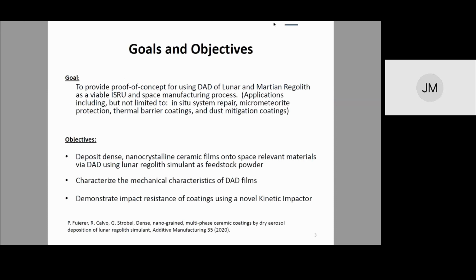The objectives were to deposit dense nanocrystalline ceramic films onto space-relevant materials using DAD with lunar regolith simulant as our feedstock powder. I also set out to characterize the mechanical characteristics of these films using a Nanovea PB1000 nano indenter and scratch tester. And I also would like to demonstrate the impact resistance of the coatings using a novel kinetic impactor. Next slide, please.